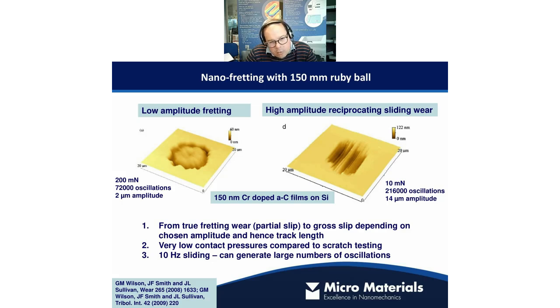So what you can see is the ball was pressed here concentrically on this circular site. And all around that site is this eroded ring of material. And that's basically because under these contact conditions, remember this is a 150 micron radius ball with 200 millinewtons applied, we've essentially got a static contact. What we've done is elastically oscillated that contact point backwards and forwards, and we've driven an erosive fatigue type behavior around that contact point. So, 72,000 oscillations to get us to that point.